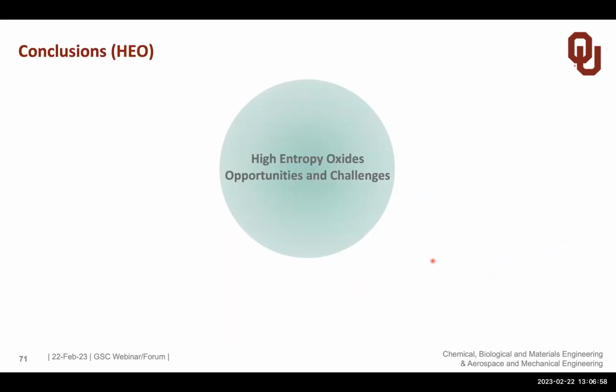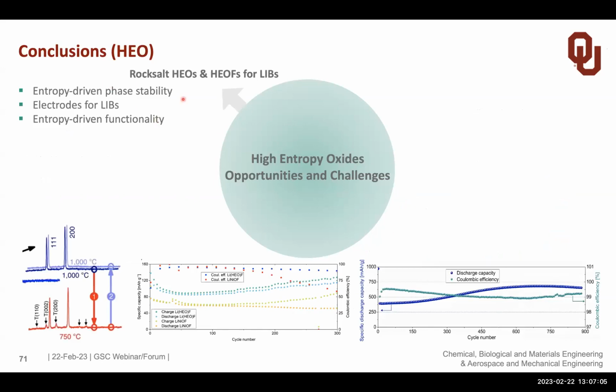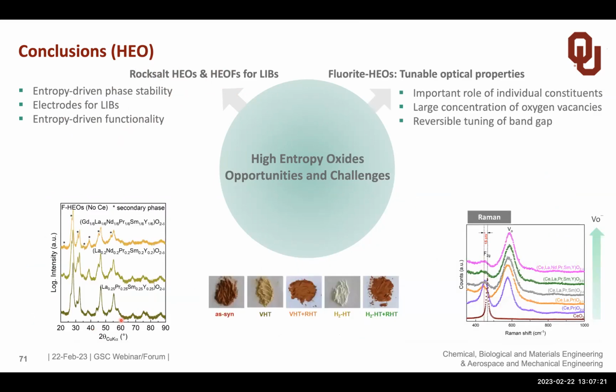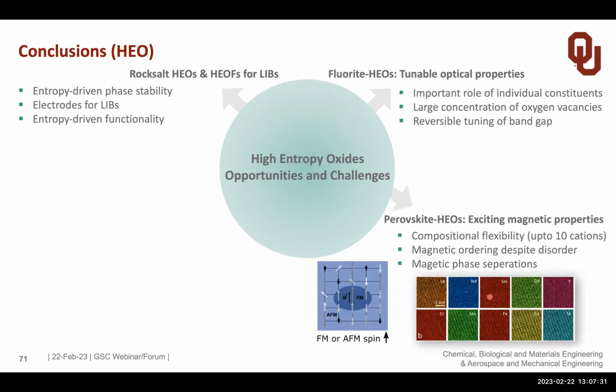So let me summarize here. High entropy oxides, opportunities and challenges. I have shown you for rock salt high entropy oxides, but also for related materials, that they have an application in electrochemical energy storage for electrodes and maybe even for electrolytes. I have shown you that fluorite types have tunable optical properties, that we can change the band gap and we can incorporate a lot of vacancies.